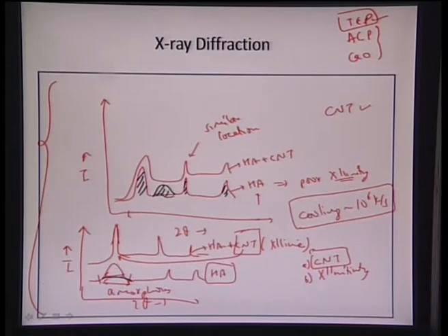So the amorphous nature can also be deducted from there, and we can find the crystallinity as only the crystalline peaks divided by the total area. That area comes out to be around 50% for only hydroxyapatite, whereas it comes to more than 80%